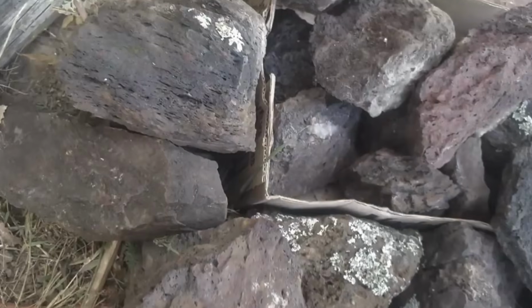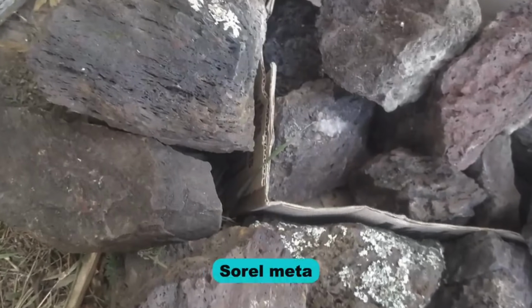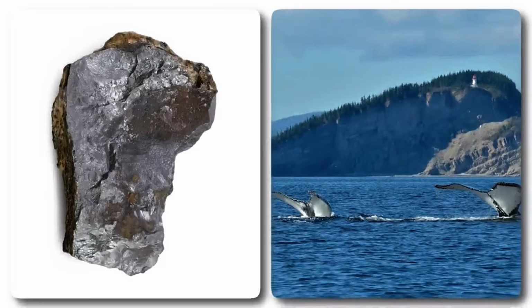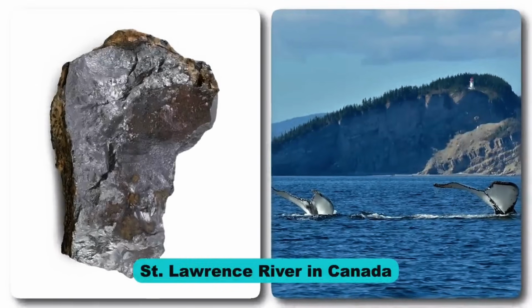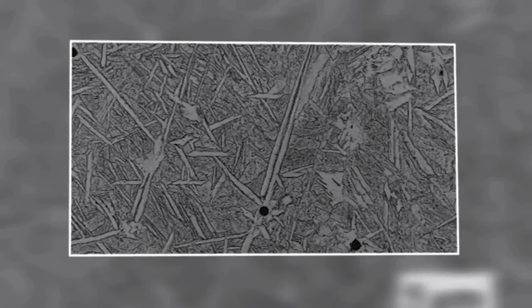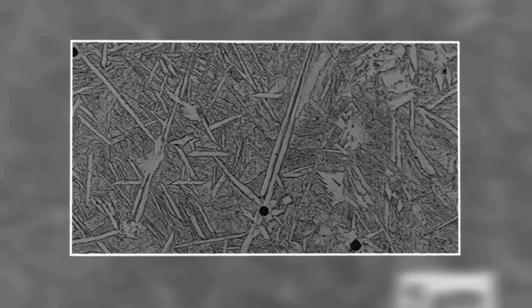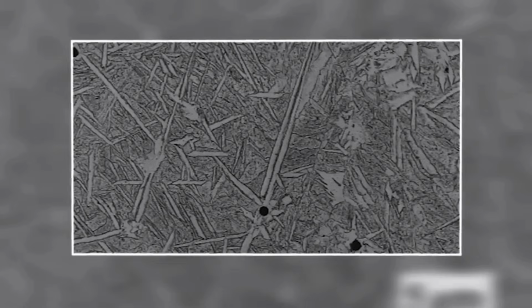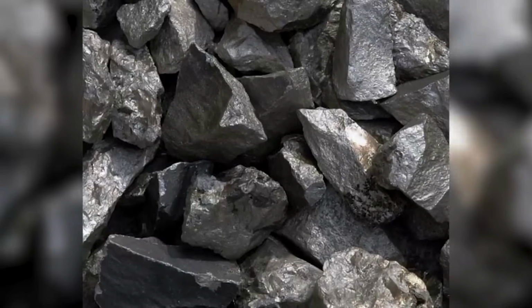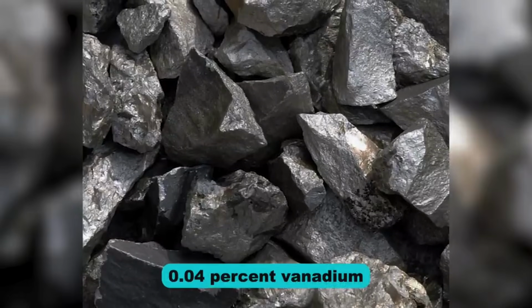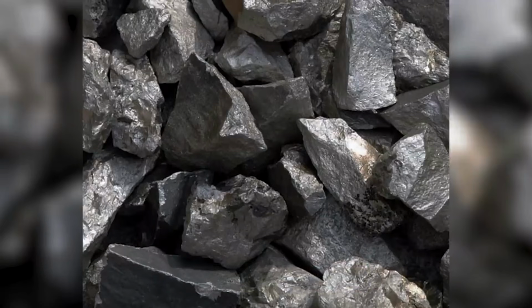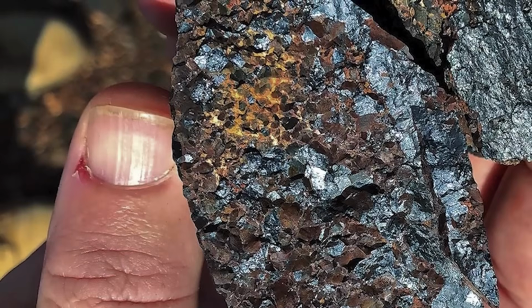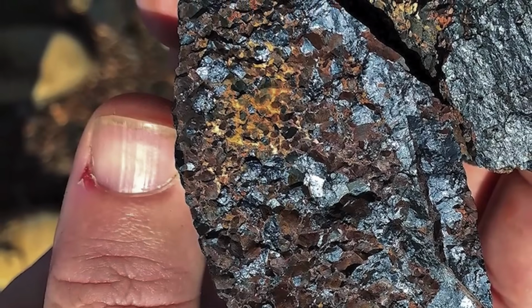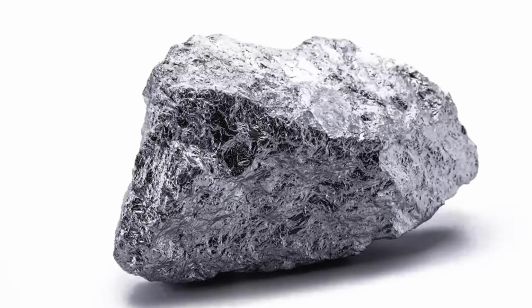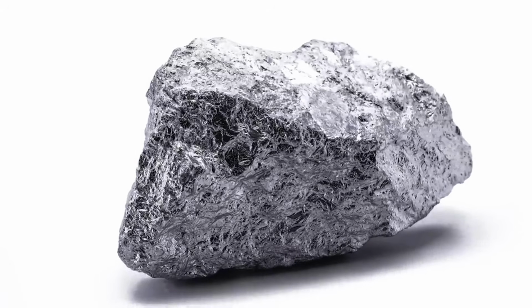Then Verhoeven switched to a different source of iron, something called Sorel metal. It was a very pure type of iron produced from ilmenite ore deposits on the St. Lawrence River in Canada, and the patterns suddenly appeared. But why? Verhoeven even ran the analysis, and in 1996 he found it. The Sorel metal contained approximately 0.04% vanadium, 400 parts per million, a trace impurity so small that no one in 200 years of study had thought to measure it. That tiny amount of vanadium turned out to be the entire secret.